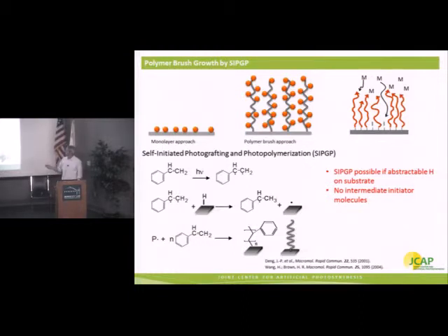So we utilize the self-initiated photografting and photopolymerization reaction. In this case, what you do is you take one of the terminated surfaces, the hydrogen-terminated silicon, OH-terminated gallium phosphide, and you immerse it into a vinyl monomer that can undergo a free radical polymerization reaction. Under UV photoactivation, you get activated monomer molecules that can then abstract a hydrogen from the surface, leaving a surface radical that can initiate that reaction, and we get polymer brush growth off of the surface.